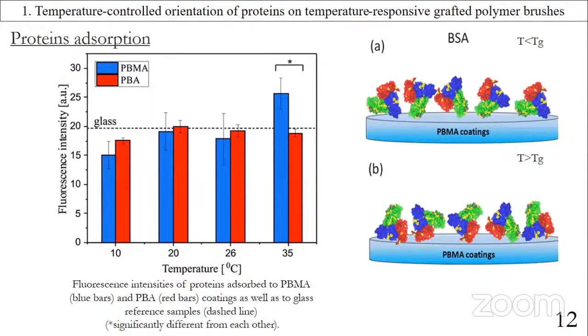Fluorescently labeled BSA was used to study the protein adsorption. For PBMA coatings, protein adsorption depicts a strong temperature dependence and increases almost twofold. In contrast, for the PBA coatings, protein adsorption displays almost no temperature dependence. That's why further studies were performed for this type of brushes. BSA consists of three domains, albumin 1, 2, and 3. Therefore, it's a very convenient object to study protein orientation.